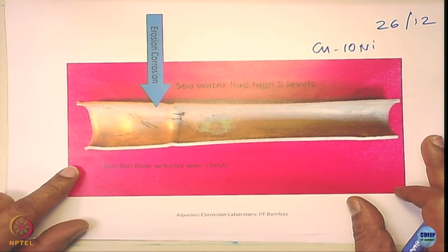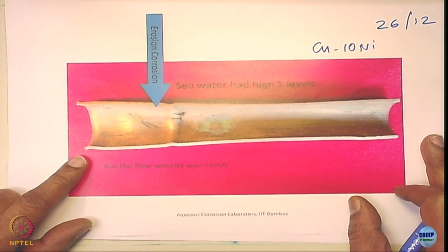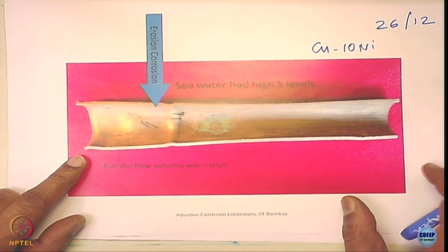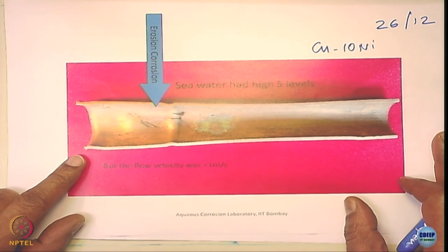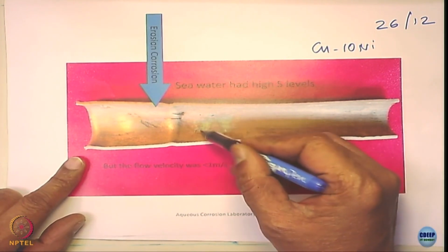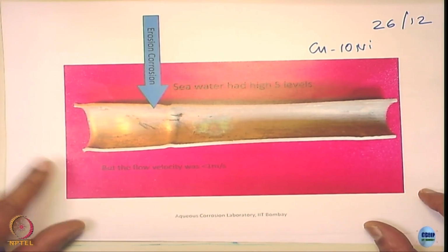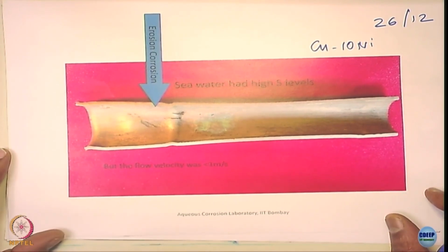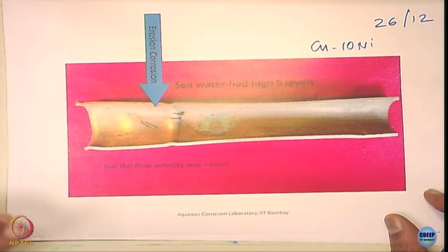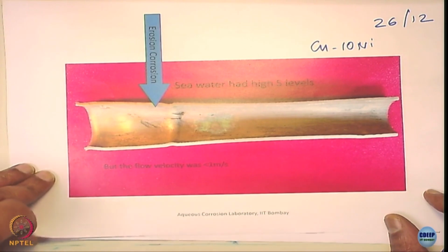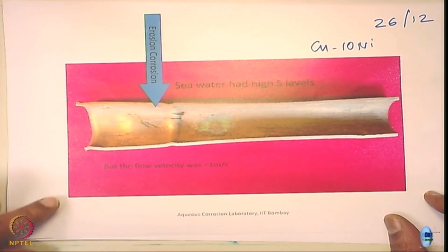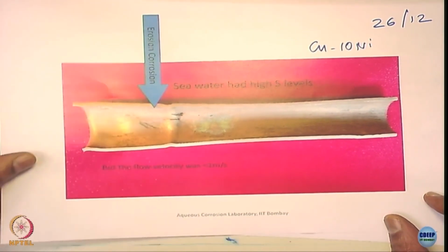They were using seawater, and stainless steel will have some problem in seawater because you may have pitting corrosion or crevice corrosion, and copper nickel alloy is supposed to be good because they do not pit. And copper nickel is certainly better from the point of view of de-alloying as compared to brass. We saw it yesterday, right. A little bit of discoloration, this little bit of green color, has happened because of the nickel dissolution process. But nevertheless, 1 meter per second is hardly a velocity and it is failing so frequently. So that was one of the problems. We will see what could be the problem in subsequent discussion. When we start analyzing erosion corrosion, we will come back to this problem and see what was the real reason for the failure of this particular heat exchanger.